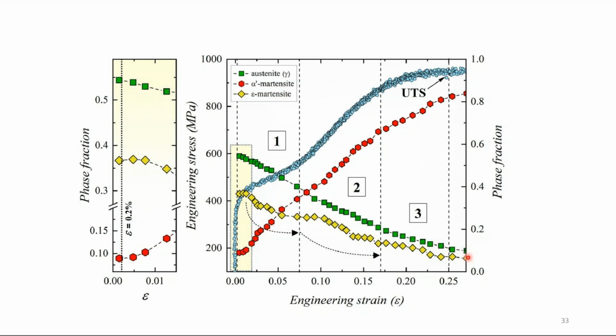And also the epsilon martensite is decreasing until you get below 10%. However, if we are reducing these two phases, we need to increase another one. What is this? Alpha prime martensite. You started with below 10%, and you are going up to 80 to 84%, let's say. So you transform this austenite and epsilon martensite to alpha prime martensite.